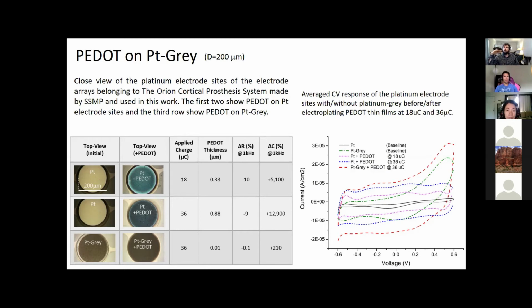So you create some covalent bonding between the PEDOT molecules and the platinum molecules, and that increases the adhesion of this coating a lot more. So I did that, and I realized after 3 times using Scotch tape, I couldn't peel them off. So I also tested them long term, and then I was like, okay, platinum gray and PEDOT together are great in terms of charge storage capacity. Let's see if platinum gray is also helping with the adhesion.